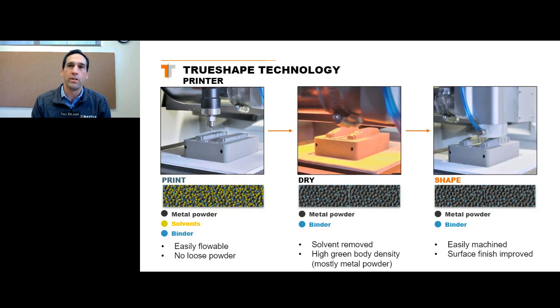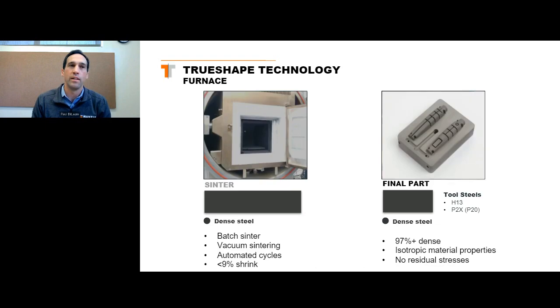And it's also in this state that we introduce the next operation, which is a machining operation or a shape refinement operation. So our process is also a hybrid process, meaning we incorporate both 3D printing and machining in order to clean up the artifacts of the printing process. So by machining, we're able to clean up the edges, we're able to remove any artifacts of the layer building that takes place from the extrusion process, and we're able to then produce a component that meets the accuracy and surface finish requirements of many forms of tooling. In this process, we'll repeat, meaning we deposit the paste, we heat and we dry it, we machine, and we do that iteratively as we build up a tooling component before finally then taking that tooling component that's been built and transferring it from our printer into a sintering furnace.